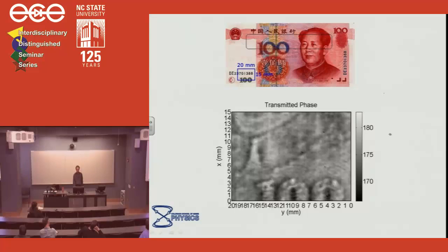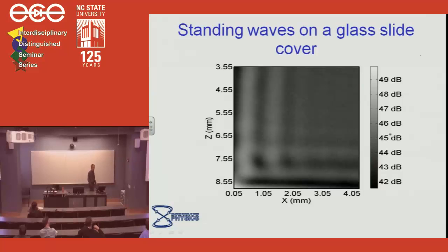Now, one of the things that's really kind of surprising is that this is a glass slide cover, not the thick slide itself, which is maybe half a millimeter or so. This is the slide cover. I forget how thick they are, but they're not very thick. And so when you scan this thing, you can actually see the standing waves set up on the glass slide. And they're caused by the impedance mismatch between the end of the glass slide and the air. So you can set up standing waves, and because it's a rectangular system, it's this perfect sinusoidal pattern in both directions. Those are just standing waves set up on a piece of glass.